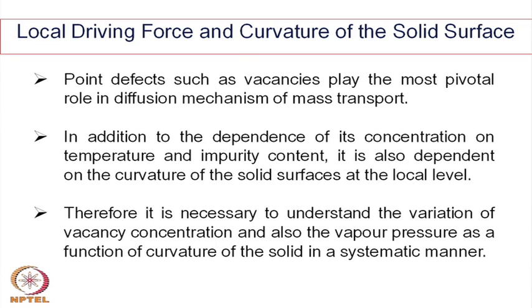In addition to the dependence of its concentration on the temperature and impurity content, it is also dependent on the curvature of the solid surfaces at the local level. We know from our discussion of point defects that they are created at a higher temperature, because at higher temperature an activation energy is provided for the creation of these defects. These defects are thermodynamic species, and creation of defects lowers the free energy of the system. Therefore, there is an exponential temperature dependence.